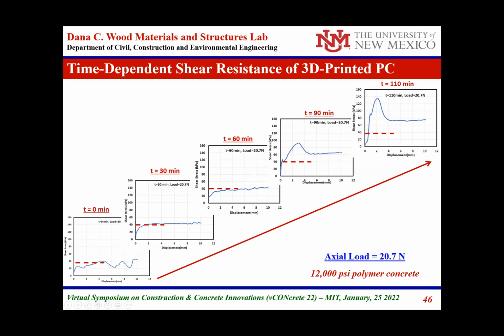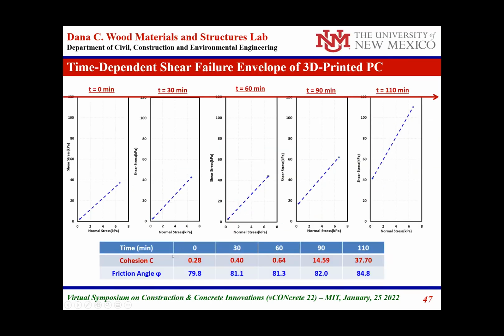We repeated the same load for different loads. Here is the case of 20.7 Newton, and you can see the material here at 0 time, 30 minutes, 60 minutes, 90, and 110. With a higher shear normal stress, the shear strength is higher. We can use these relationships to find the relationship between normal and shear stress as time passes, and the evolution of the failure envelope.